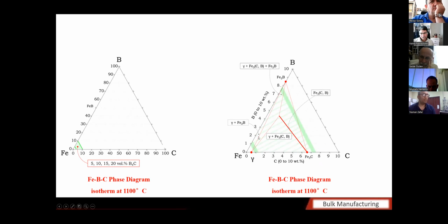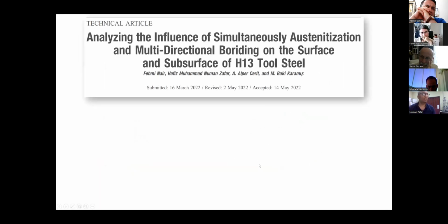And this one is a magnified version of this phase diagram. So I expect gamma and Fe2B phases to be produced at 1100 degrees centigrade. These ternary diagrams are the isotherms at 1100 degrees centigrade. If you go to 900 or 850 degrees centigrade, you will have different types of phases. So this analysis is important if you really want to have a single phase material. But there comes a question: why do you want a single phase material?